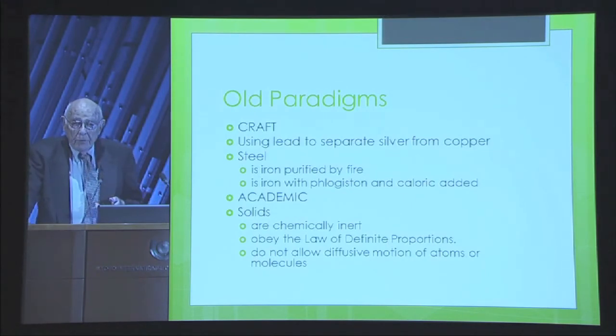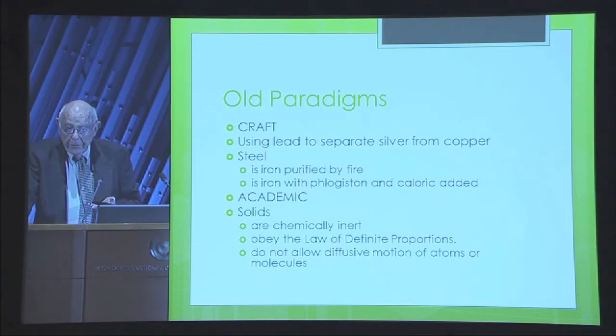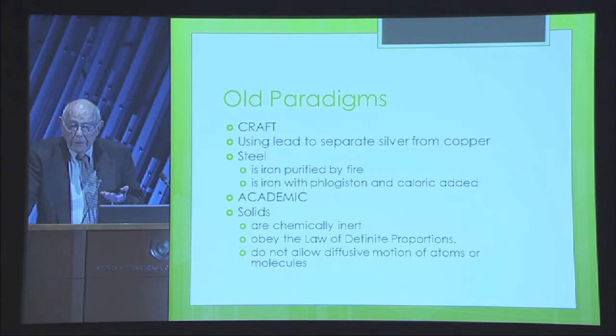The craftsman knew this. If you put gold foil on a lead statue, in 6 months it has diffused into the lead. And it was not until 1900 that somebody decided to test this, some academic, and he put the gold underneath the lead. Gold is heavier, so he didn't want gravity to push it down. And he found that it obeyed the laws of diffusion, the same laws that would be obeyed if you put ink in water and watched how it spreads.